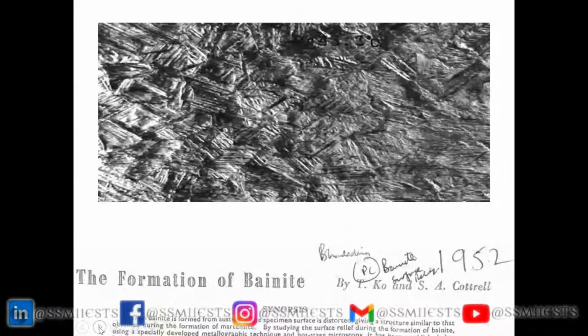So, just imagine you can get grain refinement to 1/4 of a micrometer without any imposed deformation. So processes like equal channel angular extrusion and severe plastic deformation are not terribly useful when it comes to making a commercial steel, because they focus on very small quantities of material. And here we are getting a grain refinement to 1/4 micrometer size simply because of the mechanism of transformation. If you go to the next slide.